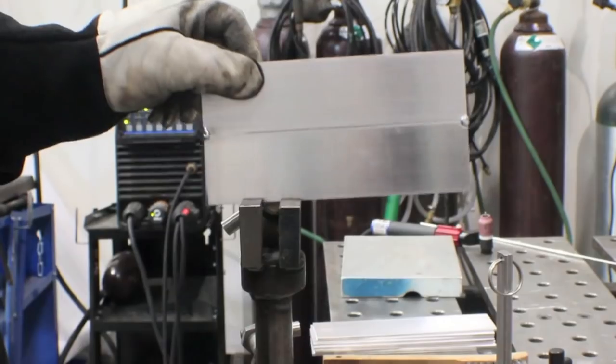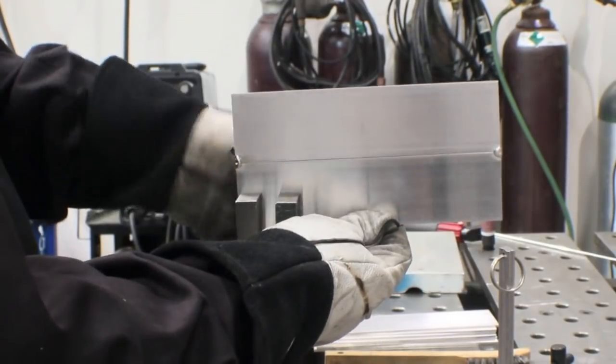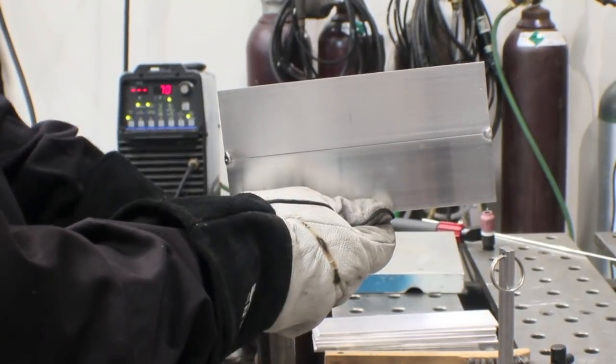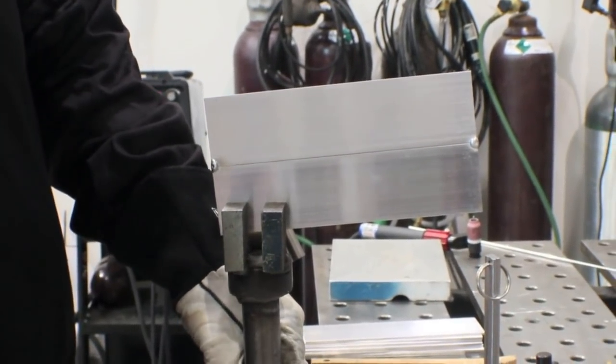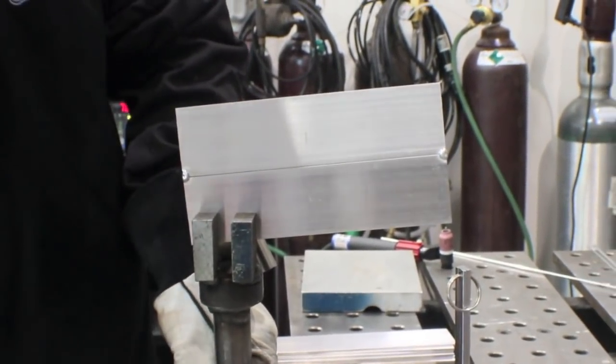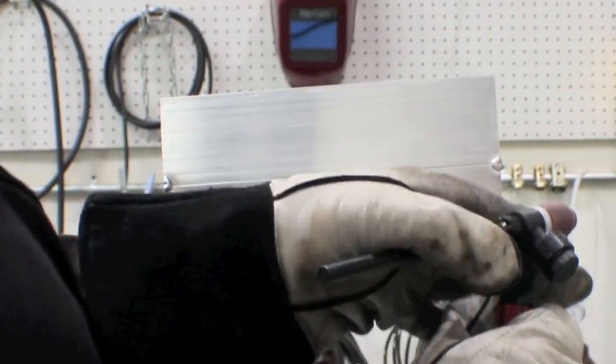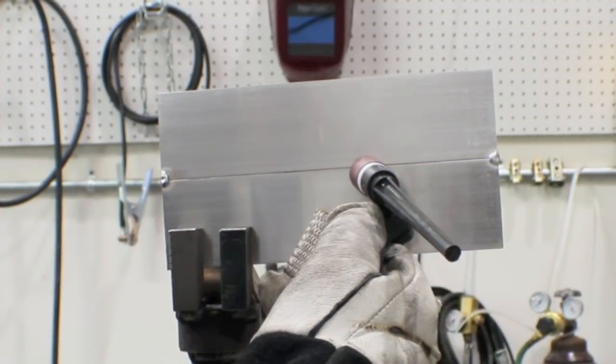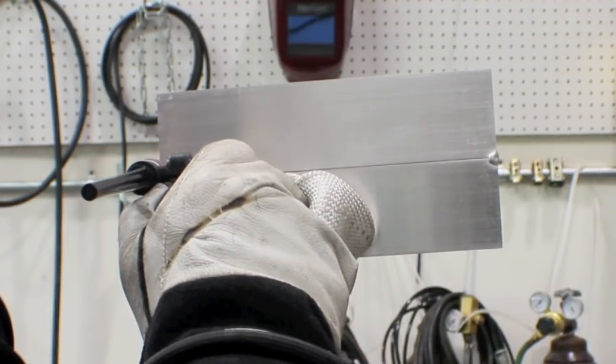After I've got the tack, you see I tweaked it a little bit so I got about a two or three degree bend in it, and that just lets it weld a little bit better. What it'll do is if you got a little bit of a tweak in it like that, it will continue going that way. Now if you start welding on a butt joint that's square and it bucks the other way, it makes it much more difficult to weld. Makes it more like welding in a valley and a T joint and it just doesn't do very well at all. This is just a practice joint, so normally when you're welding something you'll have some amount of rigidity or a roll or something bracing it. That's the reason for the two degree tweak.